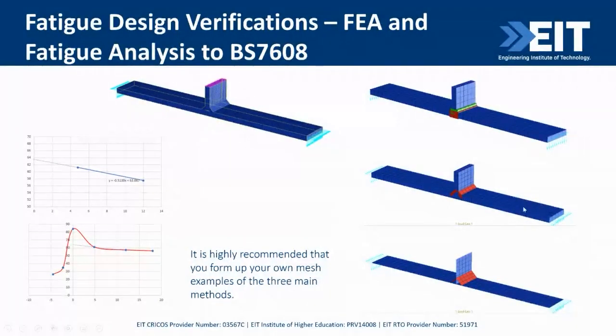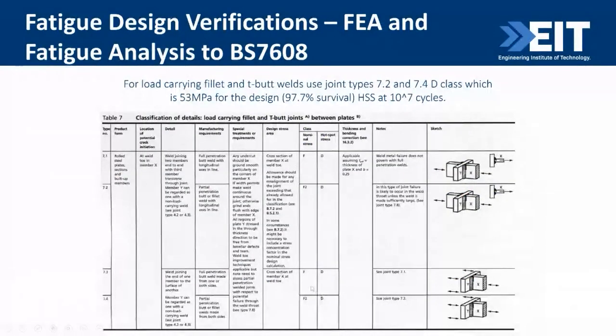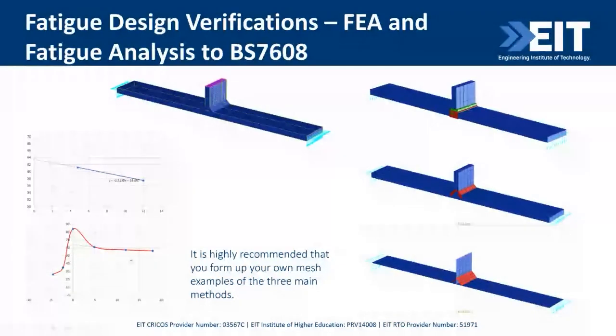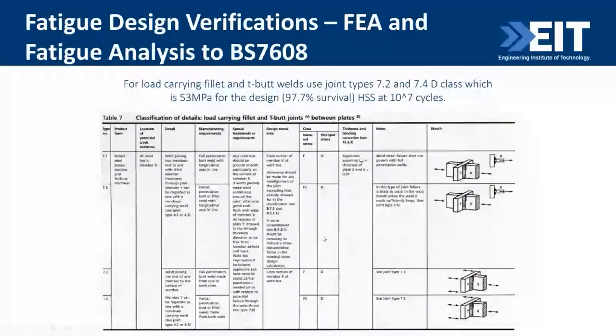inclined mesh. This is showing the plates with thickness on them. This is showing the plates with just the membrane with no thickness plotted. And if you do the bricks, you'll get that plot into the weld toe. 0 is the weld toe, always into the weld toe. And that plot is what you've seen before in the code. Stress increases into the weld, and there's your extrapolation. So that's all there is to it. So as I say before, you look at your class of your joint, and you'll compare the hotspot stress to the D line of the fatigue curves.